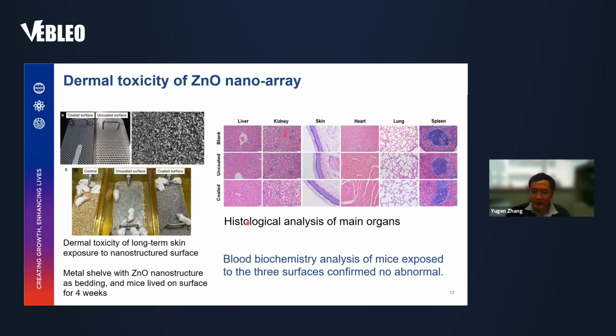For wider applications, we did this dermal toxicity test of the zinc oxide nano-array. Basically, we coated this metal shelf with nanostructure, as shown here. This is a coated one, this is a non-coated one, and this is the SEM of the surface. And then we put the mice on this metal shelf for 4 weeks. Actually, we did not see any skin issues for the control, coated and uncoated surface. From the histological analysis of main organs, there are no changes. And also blood biochemistry analysis of mice exposed to these 3 surfaces also confirmed no abnormalities. So this means this nano-array coated surface is biocompatible.